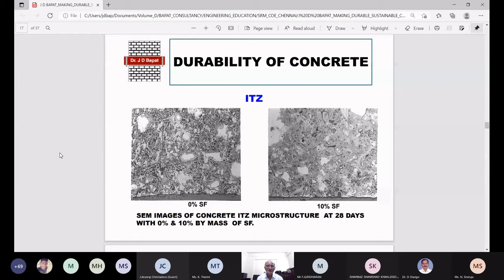Now you can see there that when I add 10% silica fume in concrete, the thickness of the transition zone will decrease. What is the impact of this? The impact of this is that there is going to be an increase in the strength of concrete, because as the thickness of ITZ decreases, the strength of concrete will increase. All structural engineers will appreciate this fact. This photograph has been taken on an actual cube.